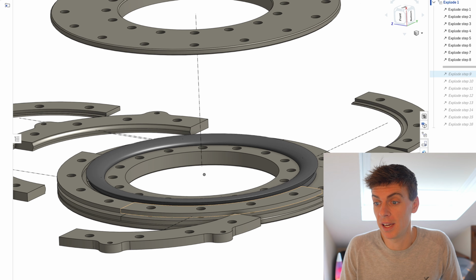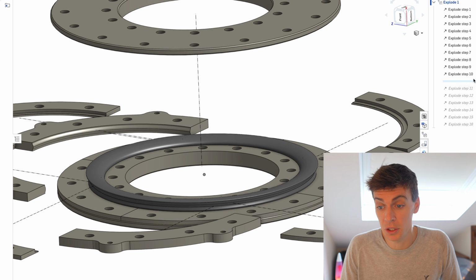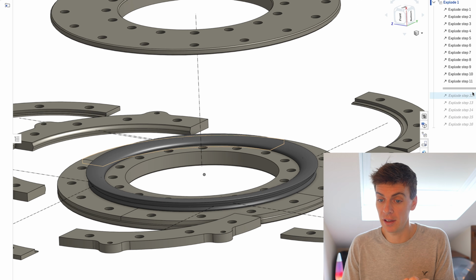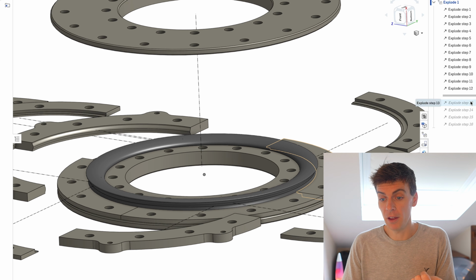And throughout this process, obviously there's resin flashing everywhere, there's overflow, and your hook is very fragile. So for the yield, if there's voids or bubbles on the hook, that rim is scrapped. And these features are actually pretty small and quite hard to mold in. So the yield of this process is lower, and the QC risk is higher because the hook is quite hard to form. One other thing worth noting is there are so many parting lines on this mold that there's a lot of space for resin to flow into, and you get a lot of flashing.